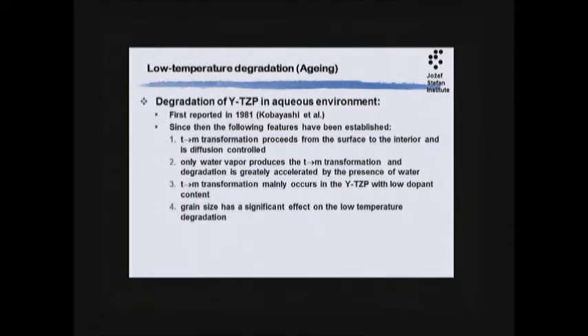Let's have a look at the aging. Aging, that's nothing new. In fact, that was very disappointing news in the time when engineering ceramics for high temperature were developed, when it was discovered that once exposed to an aqueous environment, this yttria partially stabilized material will start transforming spontaneously at slightly elevated temperatures, and water or water vapor is necessary to foster that. And it was also found that the grain size has a significant influence on that behavior.